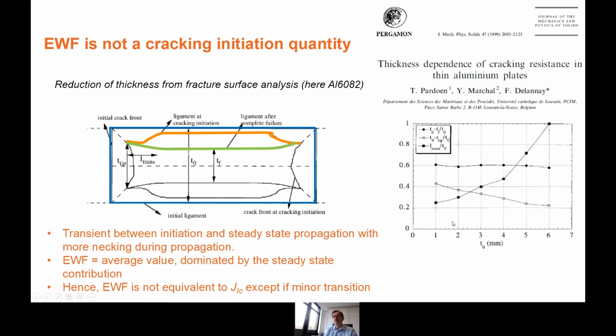So you have the two crack fronts on the left and on the right, and the rectangle is the cross-section of the ligament. The orange line is what you see if you could stop a test just at cracking initiation and monitor the thickness profile of the ligament at that point. This shows that there is a very severe reduction of thickness near the crack tip on the left and right side, and that is represented by the orange line.